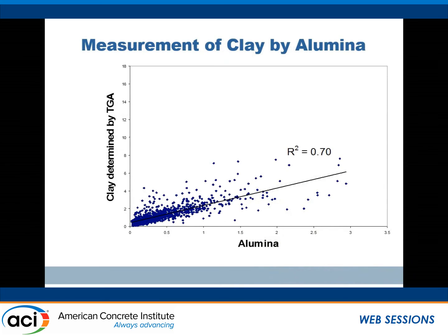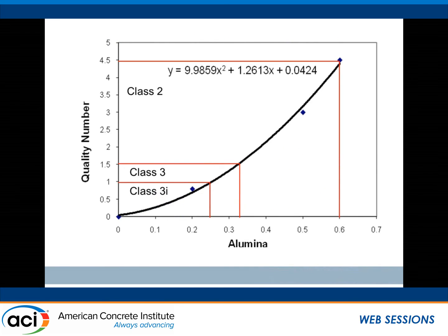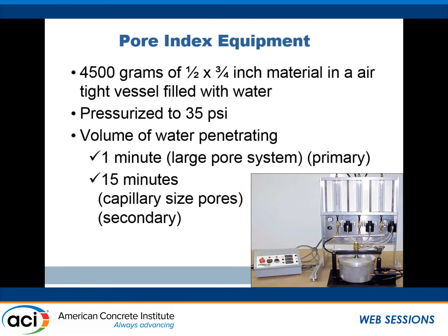They've got a fairly good correlation between clay content and alumina content. And again, they've come up with the historical data: if you have an alumina between 0.3 something and 0.6, it's not so good. And if you've got less than 0.25, it's really good. So they've classified the aggregates based on the alumina content.